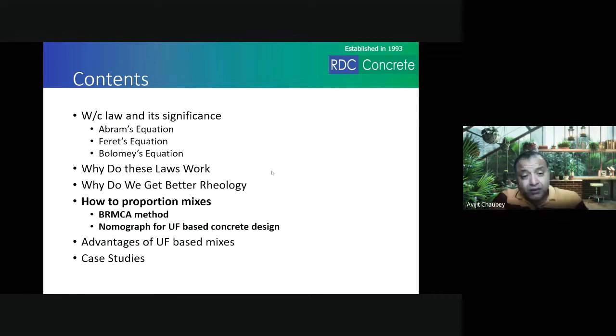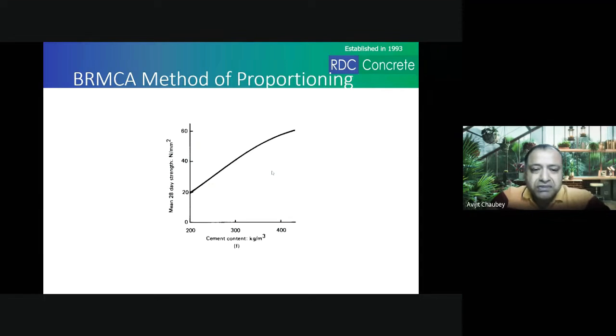The BRMCA method works the other way around. It says, don't decide the strength of concrete initially. Just do the trial with different cement contents. They don't go with water cement ratio. They say with 300 kg cement, do a trial, 350, 400, 450, 500, and measure these strengths. Plot a graph of cement content versus the strength that you get, and interpolate whatever strength you want based on this graph, and find out the cement content. That is the BRMCA method. And we have also developed a nomograph for calculating the strength of concrete for the replacement of ultrafine minerals.